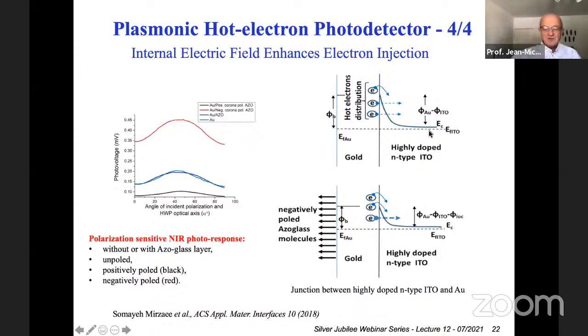Why do we have hot electron emission? That is complicated and simple. When I was saying that the electron cloud is wiggling, actually it corresponds to the Fermi level, which, if I show the energy vertical with my hand here and the position into the gold nanoparticles, is wiggling inside the nanoparticle of gold. And that wiggling of the Fermi level makes like the sea has waves, and the wave can cross the triangular barrier. So it can be modeled. Crossing and tunneling through the triangular barrier, or jumping above it, is a phenomenon that can be modeled by the Fowler-Nordheim modeling, which is an exact analytical model to describe the tunneling of electrons through a triangular barrier, technically into a metal, or from a metal into a dielectric, or from a dielectric into a metal.